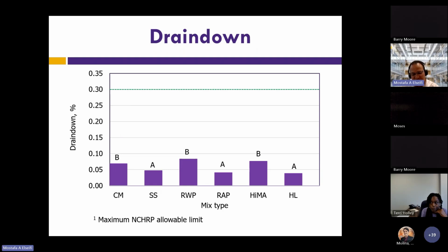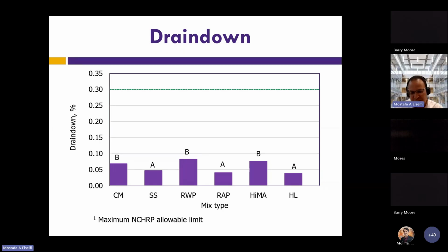All right. So the drain down, as you can see from this slide, was not an issue. We had fiber, so that really helped. The maximum drain down that we wanted was 0.3%. You can see that all the mixes were less than 0.1. So that's also very good news.